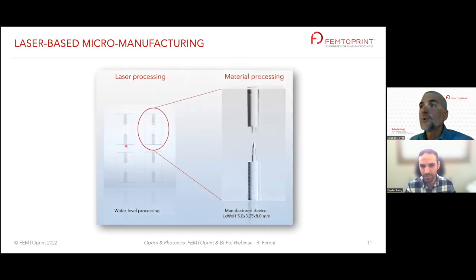So here you see an example of how our process works. You have a glass slab, and then we start writing with, imagine that the pointer is our voxel. So what we do, we write into the glass, and what you see as dark gray zones are the zones where we have written in the glass, we have fragilized the glass, and then we go into the etching process. And what we do, we singularize the component, and we open up the channels, the big channel, and here in the middle you have a microfluidic channel. That's how it works. Simple to say, it requires really a lot of know-how.